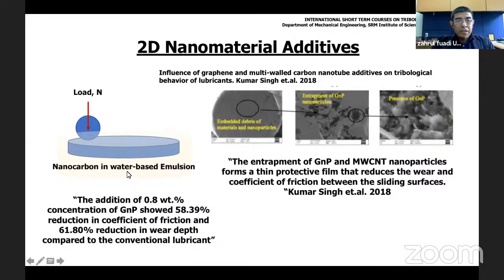And the next example is nanocarbon, which is dispersed in a water-based emulsion. Here it is shown that the graphene nanoparticle is entrapped in the pit, and this shows that this graphene has acted as a tribofilm, as a protective film that reduces the wear and coefficient of friction. And here, with the addition of only 0.8 weight percentage, it results in about 60% reduction of friction and wear.